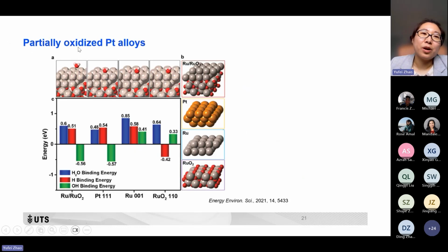And currently, we are working on the partially oxidized platinum alloys. That means the valence state of the platinum may also contribute to the performance of this HER. There is one previous publication. They investigated the reduced ruthenium oxide. It showed better performance for HER compared to the pure ruthenium and the ruthenium oxide.